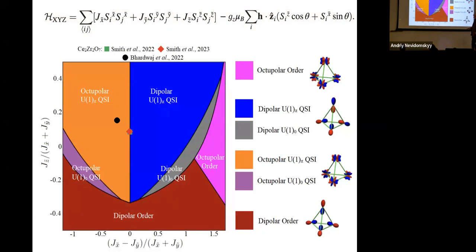So this is now showing where that sort of analysis puts cerium zirconate according to our measurements on our crystals. There are actually 2 dots here. One is our analysis in zero field, and the other is our analysis in finite field, and they agree very well with each other. But what's in some ways more amazing is independent work by Pengcheng Dai's group with Andriy and others, on an independently grown crystal, with independently done and analyzed experiments, which put cerium zirconate not exactly at the same place, but pretty close by. I consider this to be very, very good agreement.